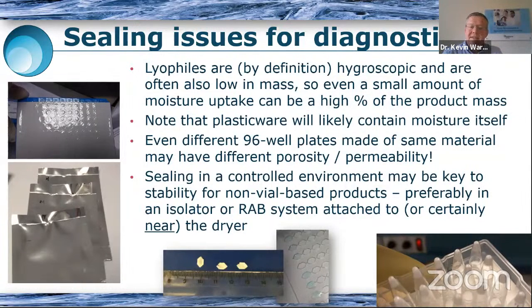We know that plasticware tends to contain moisture at the beginning of freeze drying, which doesn't always come out during freeze drying, and so we have to then optimize the secondary packaging and use things like desiccant sachets in the secondary packaging with our, in this case, a sealed 96 well plate. So you can see in the top left, we spent on this project quite a lot of time optimizing our sealing conditions in terms of the time and temperature for the heat seal, only to find that actually the 96 well plate itself was much more permeable. The plastic was much more permeable than our really good seal.